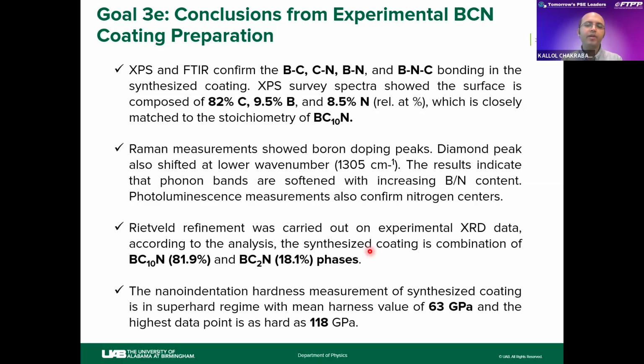We also did the Rietveld refinement for the experimental XRD pattern, which is a combination of 82% BC10N and only 18% BC2N. Nano-indentation hardness measurement of the synthesized coating is in the superhard regime with a mean hardness of 63 GPa, and the highest data point is as hard as 118 GPa.